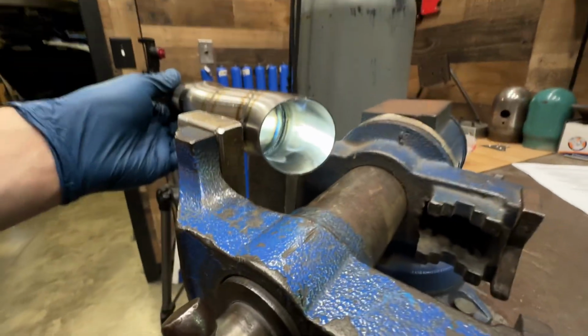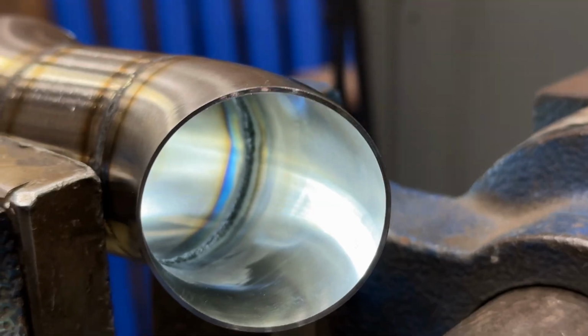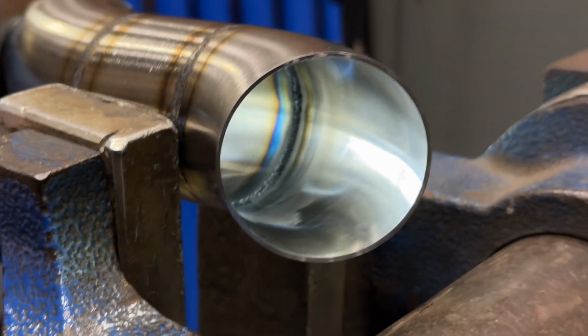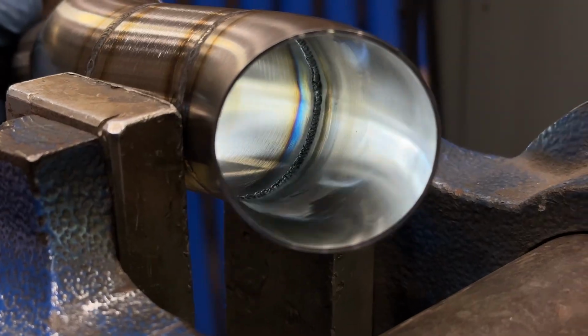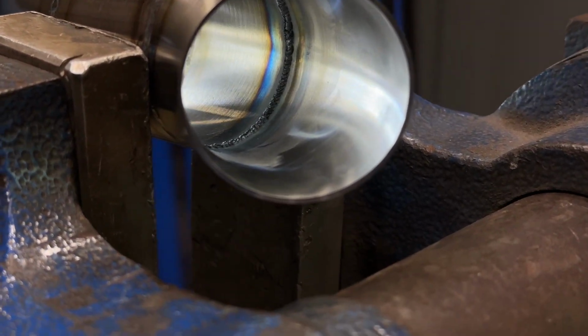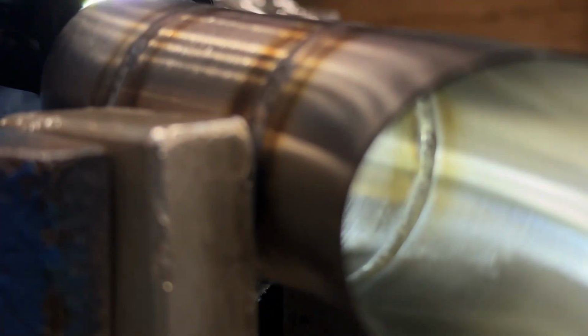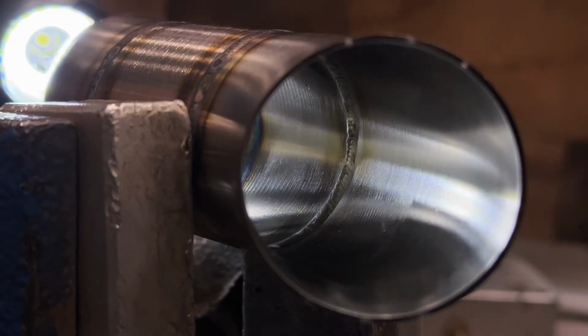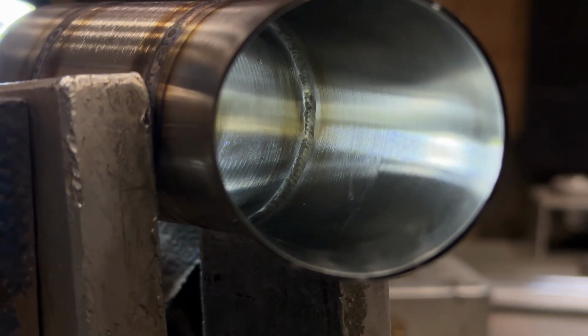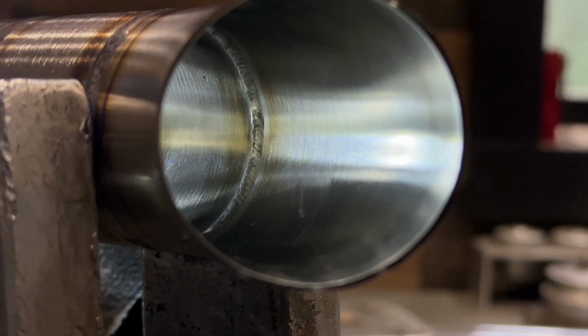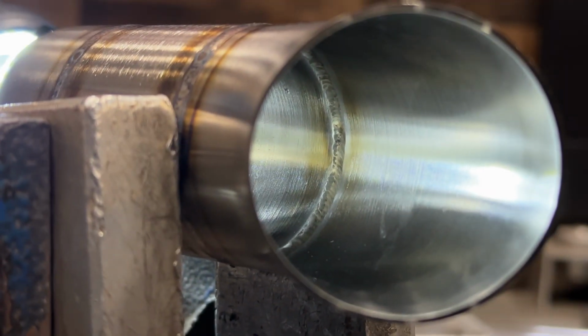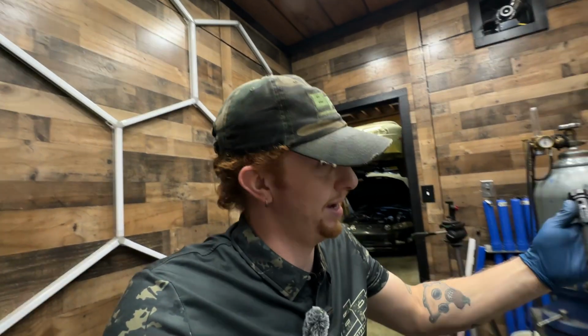Speaking of the inside, if we look at the inside of the tube, I'll zoom you guys in, and that is the non-purge side right there, which you can see all that gray, scaly nastiness on the inside, as opposed to the other side that was purged. You can see a nice smooth weld the whole way through, full penetration, no nastiness, no stalactites, stalagmites, anything like that. And that should be pretty illustrative as to why purging is as necessary as it is.